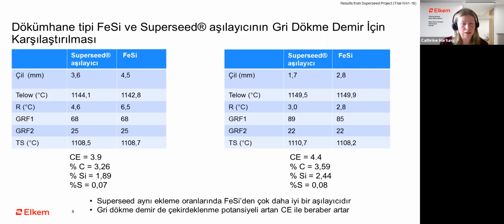If we then go to the case to the right, where you see a higher carbon equivalent, you see, first of all, that the nucleation potential is better in the iron to start with, or you have higher parameters. All the parameters look better because you already have improved the nucleation just by having changed the chemical composition. So your TE low is higher compared to the lower carbon equivalent iron. As a result, the chill you measure is lower both for Superseed and ferrosilicon. And the recalescence is lower. You have a higher graphite factor 1. You have a longer time in which the graphite is precipitating. And of course, more graphite is precipitating as a result of this, that you also have more carbon available.